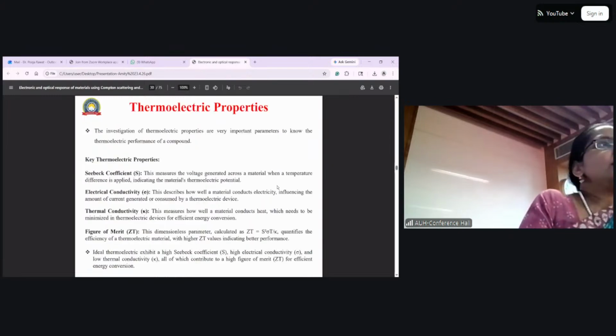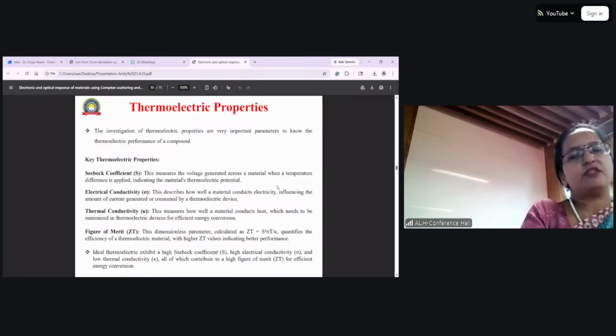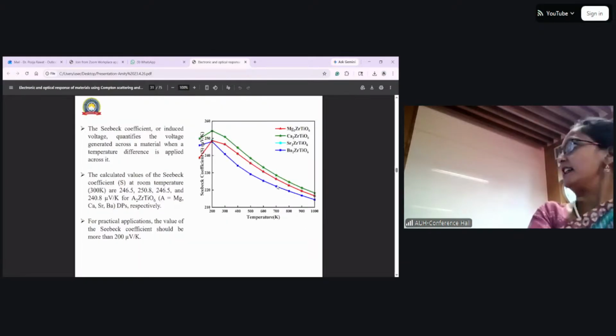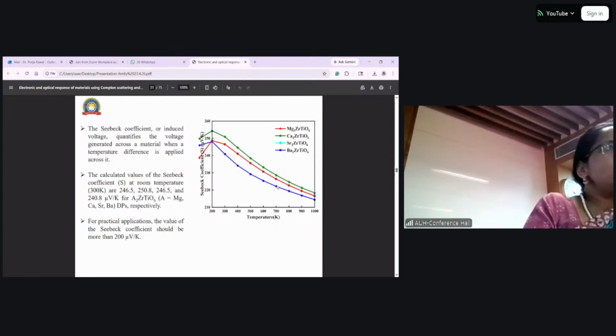Then to check the thermoelectric application of these materials, we have calculated certain parameters. The Seebeck coefficient, which measures if I am changing the temperature, how much voltage will be generated. What is the electrical conductivity? What is the thermal conductivity? Then there is a parameter termed the figure of merit that we have calculated. So for the practical application, the Seebeck coefficient value should be greater than 200 microvolt per Kelvin. It means if I am changing the temperature by 1 Kelvin, how much voltage will be generated?